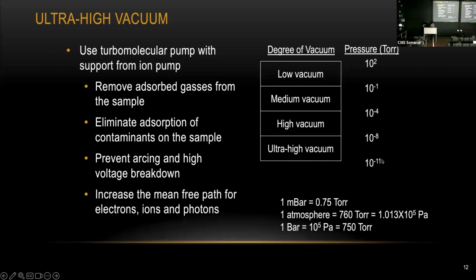By doing the measurement in an ultra high vacuum chamber, we can remove any contamination on the surface, any air molecule, any water molecule you have on the surface. We're going to generate X-ray, so we need high voltage, and the ultra high vacuum chamber can prevent arcing from high voltage breakdown. And most importantly, by doing the measurement in a UHV chamber, we can increase the mean free path for all the particles you are dealing with.